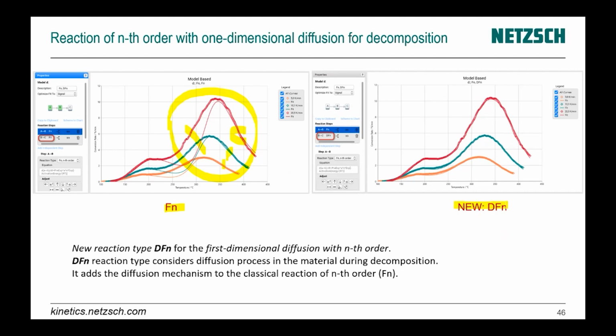And if we use here our new reaction diffusion with nth order, then we have a very nice fit for this type of curve. It could be used typically for decomposition of polymers. For example, for industrial processes, industrial sintering processes, for the debinding process during production of ceramics or during metal sintering. It could also be seen for the pyrolysis reaction, where we have some reactions which could not be described by the classical reaction of nth order and could not, of course, be described by the classical reaction of diffusion. But it could be well described by the new reaction of diffusion with nth order.